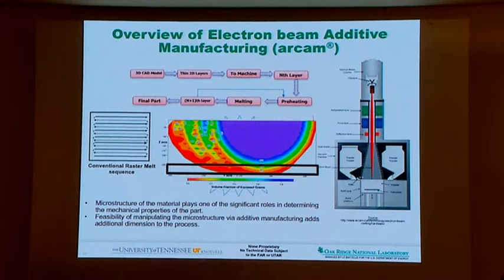So let's say that blue is a melt pool moving on this substrate. And if you shrink yourself to the atomic level and walk along that, you will see on one side the hot region, on the other side the cold region. So if I know the distance, delta T by delta X will give you a thermal gradient. And then this melt pool is moving at a velocity given by, let's say, the beam velocity. However, on the sides, they are actually moving at much different velocities. So the velocity along this melt pool will not be the same. And this is the beauty of weld pool solidification. You get different magnitudes of thermal gradient, which we call G, and different magnitudes of liquid-solid interface velocity, R. So G and R are varying across the melt pool.